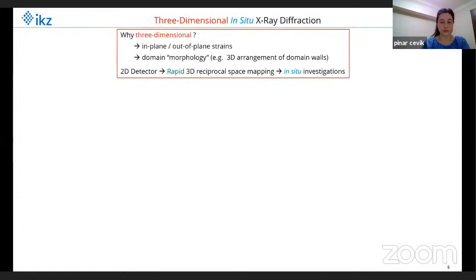In order to get this information, we have performed three-dimensional in situ X-ray diffraction. So why three-dimensional? Because on one hand side, the strains themselves are three-dimensional in their nature. We have in-plane strains, we have out-of-plane strains, we have shearing in different directions. So this is all 3D. On the other hand, the domain morphology, so the arrangement of the domain walls, is also 3D. Therefore, we have to measure the intensity distribution in reciprocal space in all 3 dimensions.